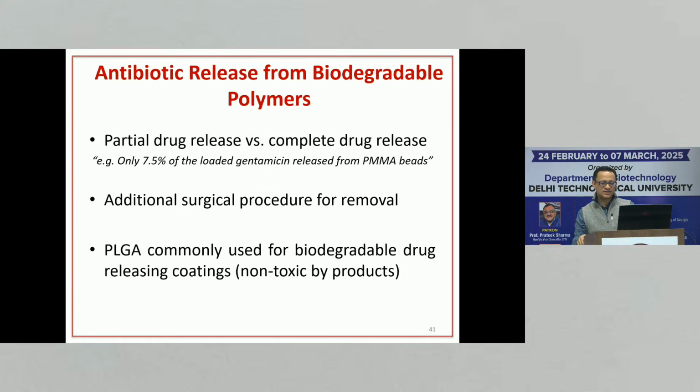That biodegradable idea that I was talking about. There was this study, partial drug release versus complete drug release. They showed that only 7.5% of loaded gentamicin was released from PMMA beads. But for PLGA, you can release the whole drug, whereas in this study, only 10% of the drug was released. But if you make biodegradable particles, you can release everything.